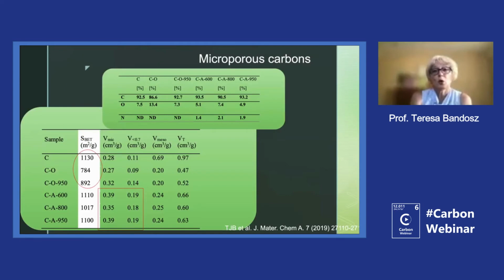So then we look at microporous carbons. And here it is an interesting story, because in this case we modified carbon as before, so we oxidized, but nitrogen was introduced from ammonia, and we were more successful with introduction of nitrogen. We had a little bit more, but what we found, that those carbons with nitrogen, the porosity was almost the same for all samples. But for carbons which were not modified, we had the differences in the surface area, in the volume of ultramicropores.